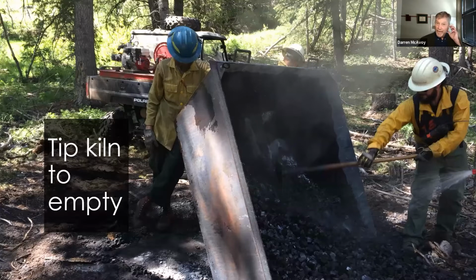So biochar is not ash, it's a completely different material. We don't produce a lot of ash in this, but a little bit. Most of it tends to get washed off during the quenching process. A few strong backs or possibly an ATV or something could be used to tip the kiln, and they can be fairly heavy at this point. The kilns themselves weigh about 200 pounds when they're empty and dry. So we tip the kiln out and pull our biochar out of that. We always want to make sure we have a fire line around this area first.